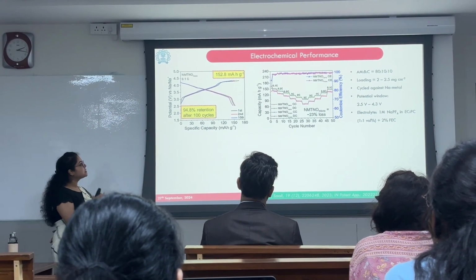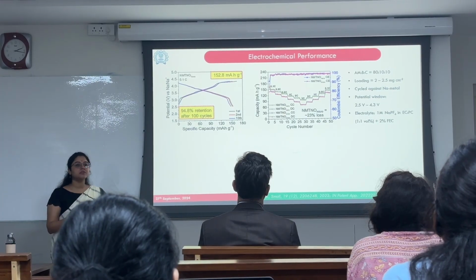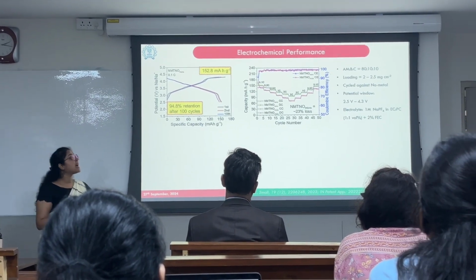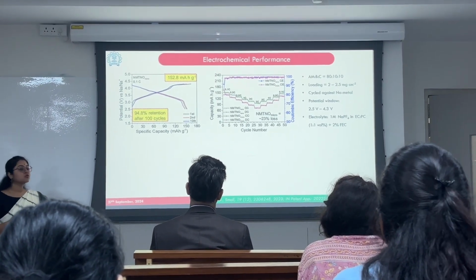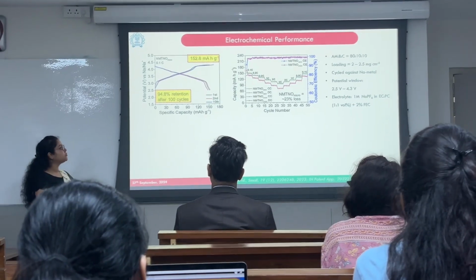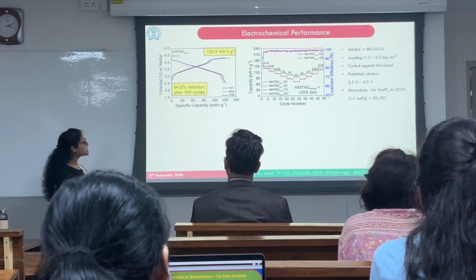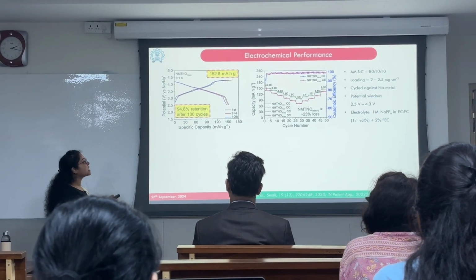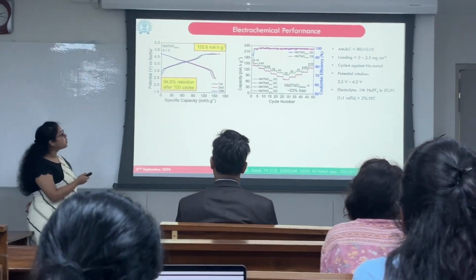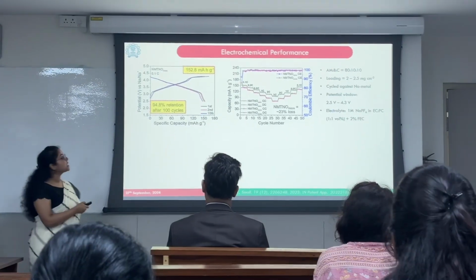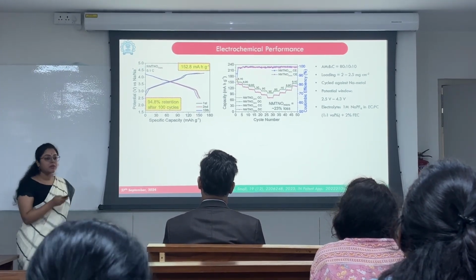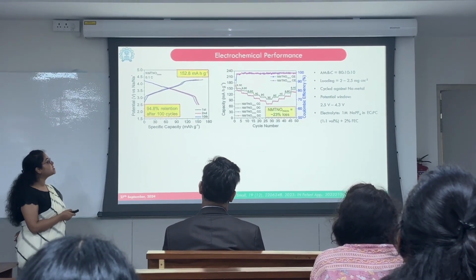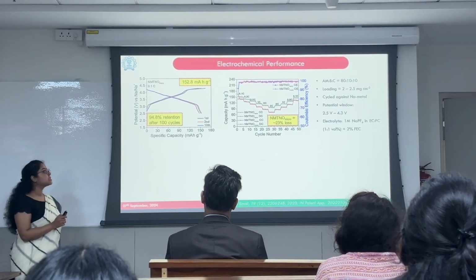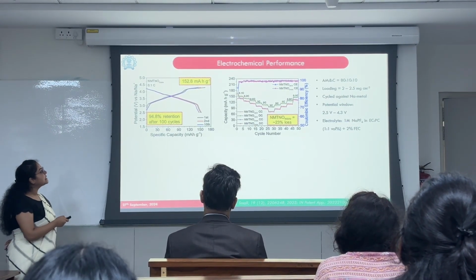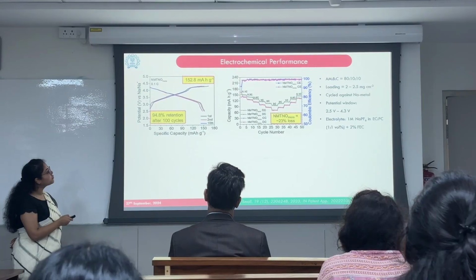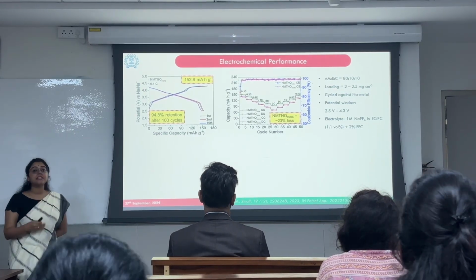We also tested the rate capability in order to see the reversibility of the sodium ions, because as we have made nano, it would give a shorter diffusion pathway for sodium ions. According to our hypothesis as well as the experiments, it performed very well even at a higher C rate of 3C. In contrast, the NMTNO micro suffered a 23% loss, and it is to be noted that as the C rate increased, the performance of NMTNO micro degraded further.